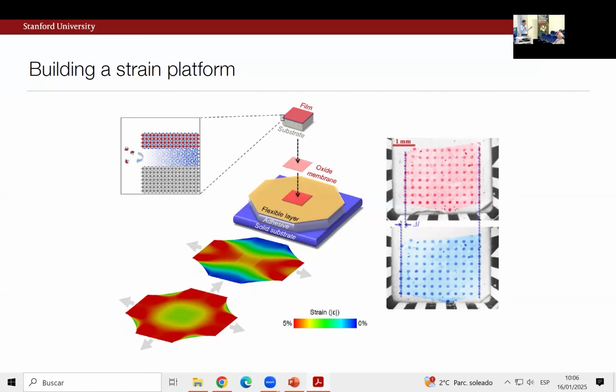If you use hydrostatic pressure, well, ideally it's hydrostatic. If you use lattice strain, it follows the symmetry of the lattice. So in principle, if you had some theoretical idea, put a strain in this weird random direction, that degree of freedom exists. And we haven't really quite used it yet, but I'll show you some stuff at the end.